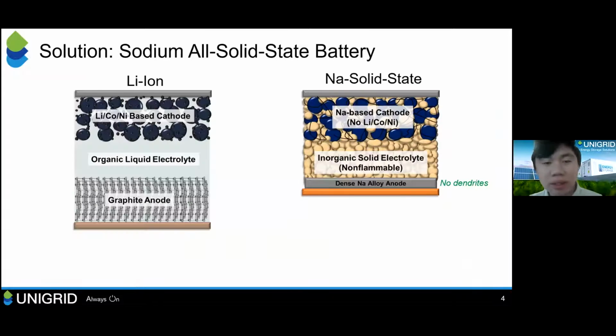So what is our solution in Unigrid? To this end, we are proposing the use of a sodium solid-state battery to address these problems. Now, compared to a lithium-ion battery, the chemistry itself is quite different. Firstly, lithium-ion batteries often comprise a transition metal-based cathode, something that contains lithium, cobalt, nickel, often manganese as well, and oxygen. And you also have a liquid electrolyte to transport the ions, as well as a graphite-based anode as a counter electrode.